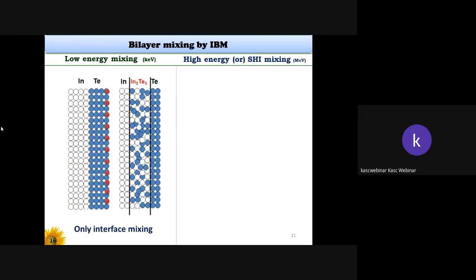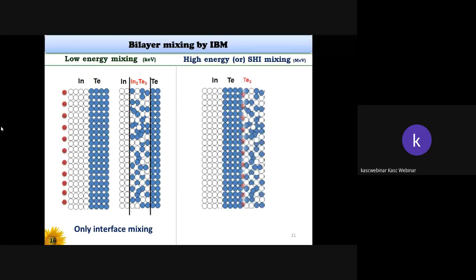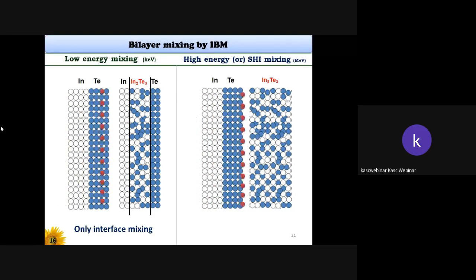As I said, the first diagram clearly represents the intermediate state of a sample. I have chosen an indium and tellurium bilayer sample, which was irradiated with the help of an 80 MeV oxygen ion. And at the end of the process, I got only the intermediate state of In2Te3 or indium telluride sample. But at adjacent sites, there may be a little trace amount of indium layer and tellurium layer. While I am moving to swift heavy ion irradiation by using gold ion and silver ion of 150 MeV, it can result in the complete mixing of the indium and tellurium layers to form indium telluride.